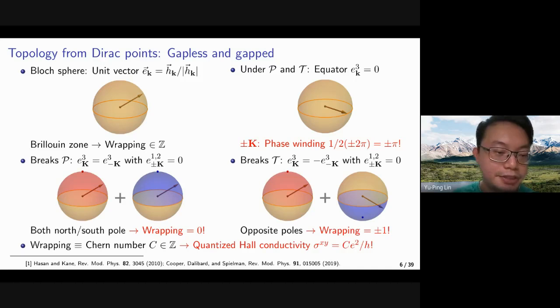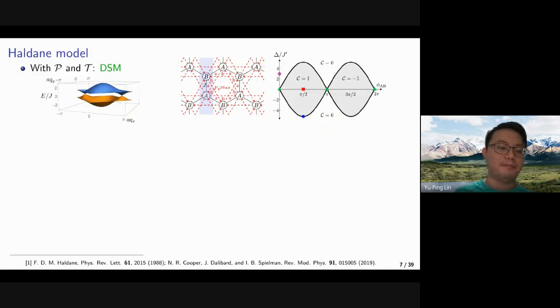So the wrapping number could actually be identified with the Chern number of the band. And the Chern number can be thought of as a quantized geometric phase when we go around the Brillouin zone, and it is an integer. An important physical realization of the Chern number is that if we apply an electric field in the x direction, there will be a response of the current in the y direction, and this kind of Hall conductivity will be quantized, and the quantization is defined by the Chern number. And this will give the non-trivial topology of the band structure. So there is a proposed realization of this kind of topologies, which was posted by Haldane back in 1988.